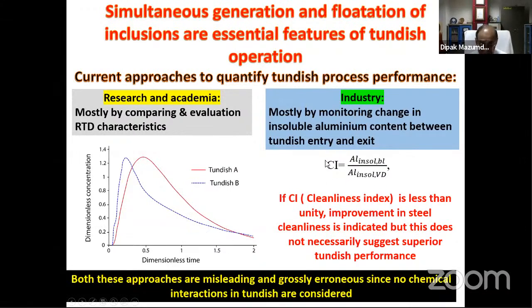Similarly, the cleanliness index in the steel industry, or flotation of non-metallic inclusion, is determined by using this particular criterion. When we say aluminum insoluble, what does it mean? It means Al2O3, which is solid. In the ladle, divided by the aluminum insoluble or alumina content in VD, which essentially means that if aluminum insoluble in VD is equal to aluminum insoluble in ladle, that means no inclusion has floated and the cleanliness index is equal to 1. But again, this has nothing to do with the reoxidation that takes place.